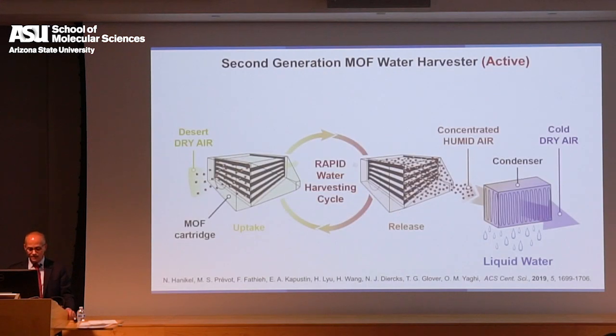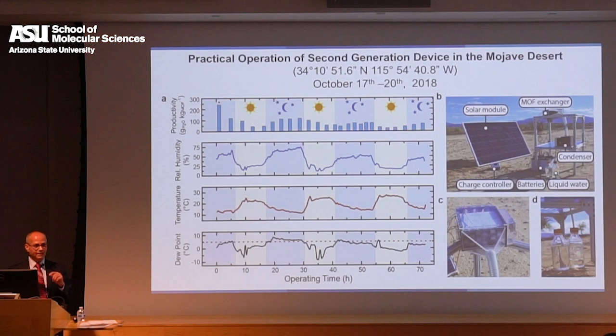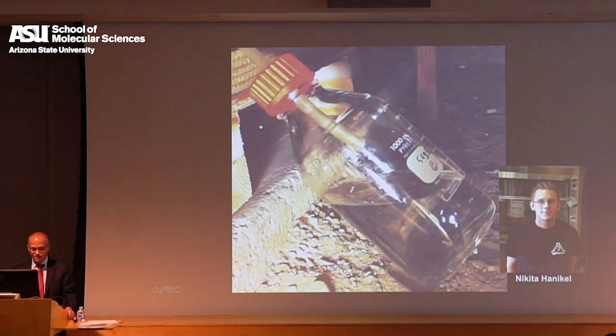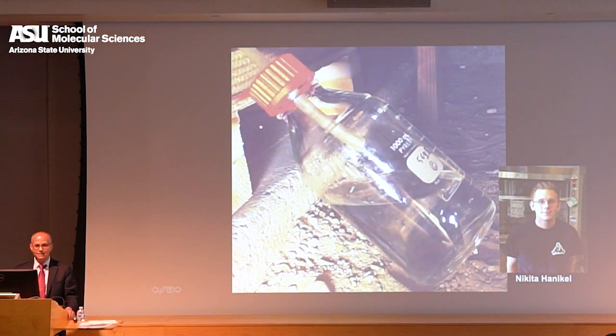Okay, I just want to say that we took a kilogram of that MOF to the desert, Mojave Desert, and you can see here the humidity in the desert at this time of the year when we tested this and the uptake of water. Ignore the first bar because that's the water that was in the MOF when we were in Berkeley, but this is in the desert. And you can see that even at very low humidity, less than 10% relative humidity here or 10% relative humidity, it still picks up water. Okay? And my students know not to return without the evidence of water, real evidence of water being picked up from air.